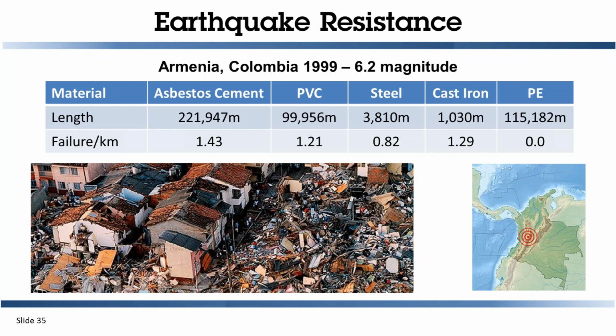A couple case studies. Armenia, Colombia, 1999. You see the length of pipelines, and then you have failures per kilometer. Polyethylene had 0 failures in this earthquake. And even it was a devastating earthquake. The PE pipe, whether it was transporting water or gas, it still might need to be inspected after the quake for replacement opportunities. But the bottom line is it did not fail catastrophically.